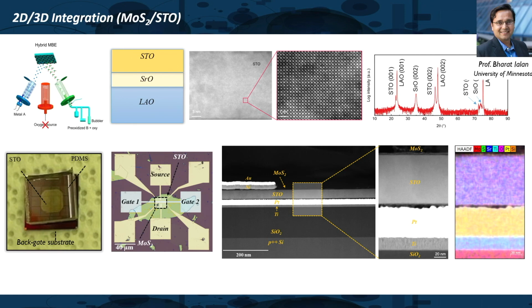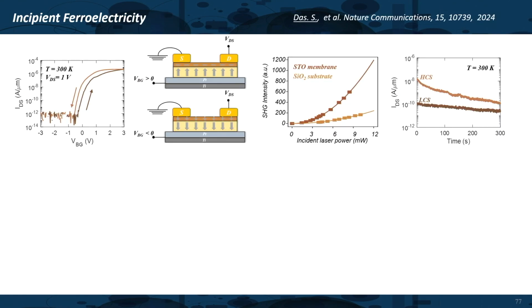So in this kind of a device, we found that we have something called incipient ferroelectricity, where you get this counterclockwise hysteresis in the MoS2 gated by STO. We got some polar order from the second harmonic generation measurement, but one thing which was not very good was that the retention was very poor, because in a FET you should have two polarization states that are stable, but because it is an incipient ferroelectric material, it depolarizes very quickly.